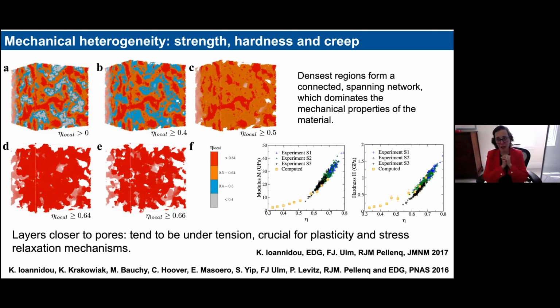And so if you start to think about where the possible origins of plasticity and stress relaxation in this material are, and I'll tell you in a minute why, then you can identify with this type of study where plastic processes are more likely to occur, where stress heterogeneities develop in the material. And I'm trying now to go back to the structure and understand the type of stress heterogeneities that you sort of freeze in this structure as the gelation process develops.